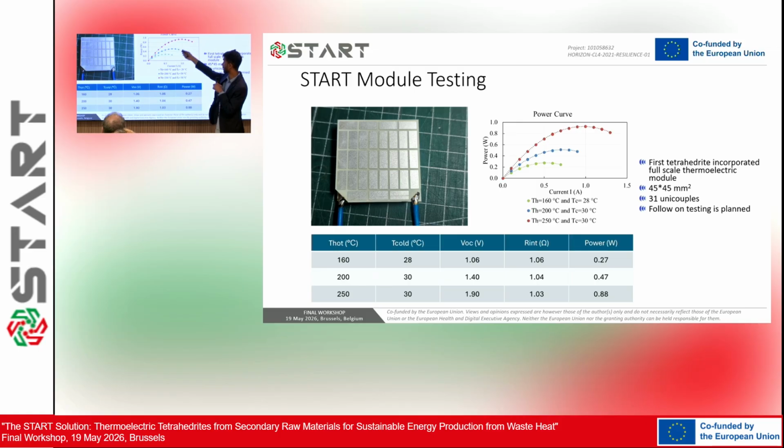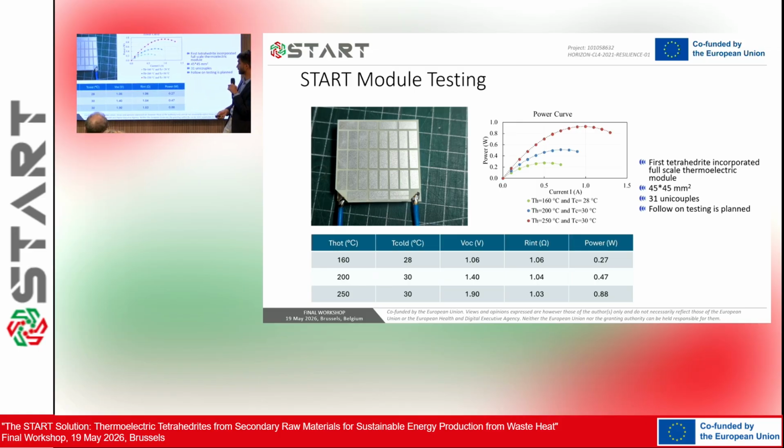So here you see, we are able to generate 1 watt for now at a T hot of 250 degrees centigrade. That's quite exciting, that this module works. It has survived. It has come out of the testing system without breaking. So that's also good. We can continue testing till the end of the project. And it's a key output of the project itself.